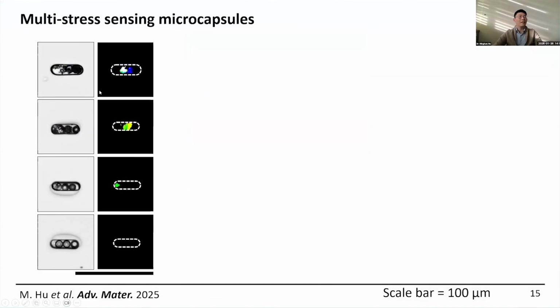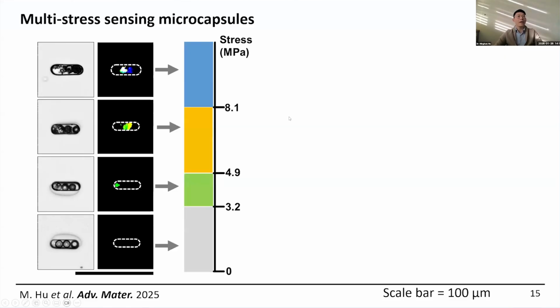Okay, then with that, we first do the breaking test as I did before. We can see that if no microcapsules are broken, with no applied force, there is no fluorescent signal. If only one is broken, we can see the green signal from the first microcapsule. And if we have a higher force, we can see 2 microcapsules broken, and we have the mixed signal between the yellow and green fluorescent colors. And if they're all broken by the highest force, then we also have the 3rd color. In this case, we can translate this color tone to match the different stress ranges.